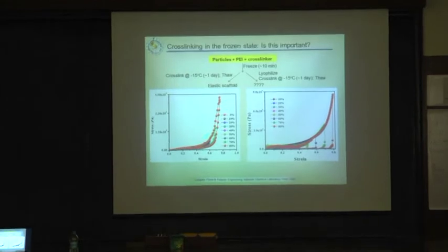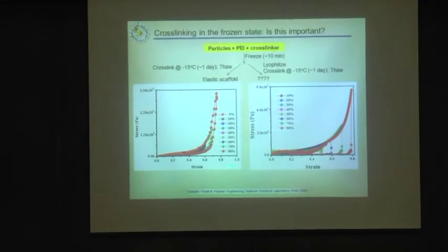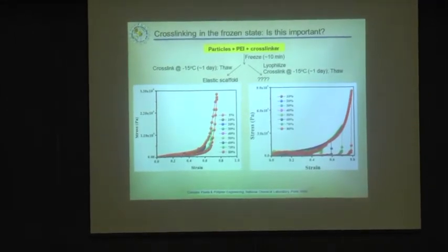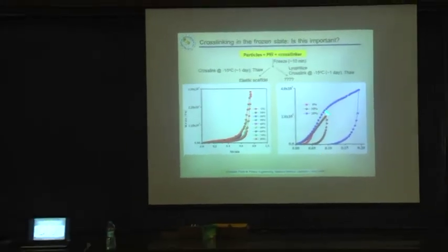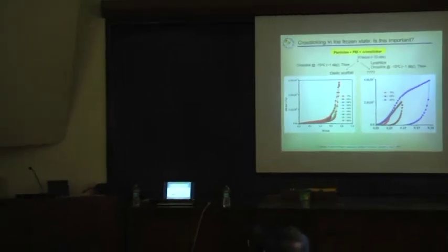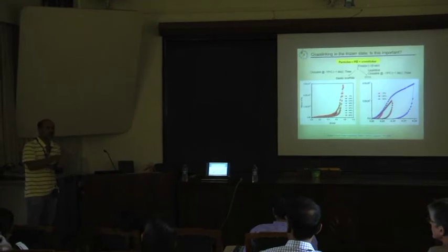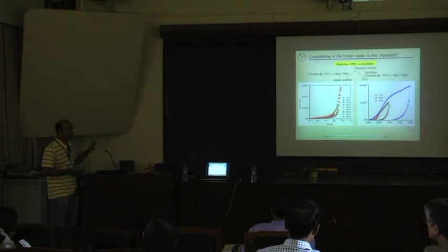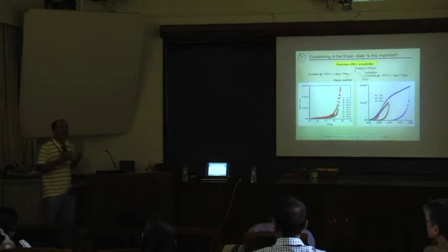And so if you look at the stress strain curve for these materials, unlike the previous curves where the stress would come back as you decrease the strain, essentially you have this massive failure. In fact, you start seeing failure at as small as 5%. So this is what you would normally expect. You take particles together, it's a huge amount of inorganic, you put a little bit of strain on it, and it falls apart, right? Somehow what this tells us is that the structure that we are developing with the ice crystals pushing these particles together, and then if the cross-linking happens, you get this sort of unique structure that allows you to relax back to its original position.